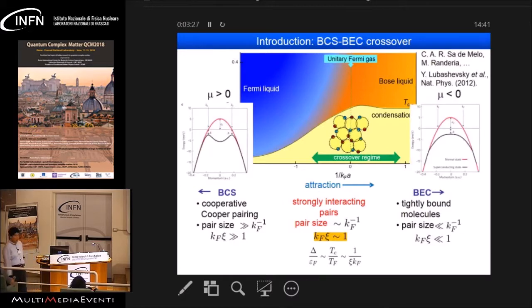If you look at the electronic structure, let's suppose we have one hole band, as shown by the red curve. In the BCS state, in the superconducting state below Tc, we have a gap opening at the Fermi wave vector kF. But in the case of the BEC limit, the chemical potential becomes negative. So the minimum gap opens at k equals 0, not at k equals kF. So we have this kind of convex up curvature in the superconducting state.